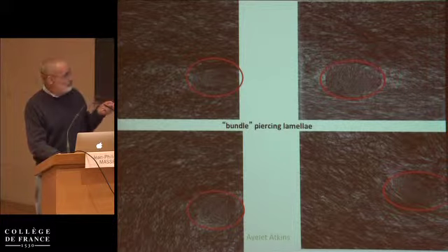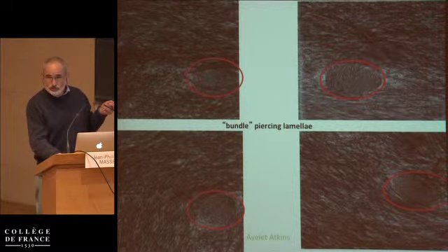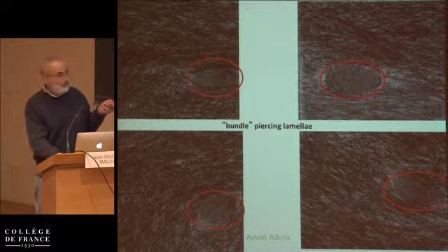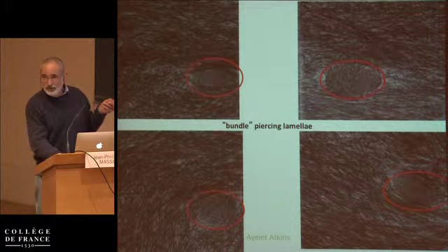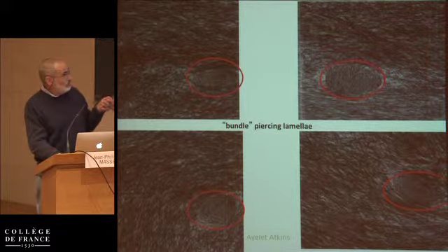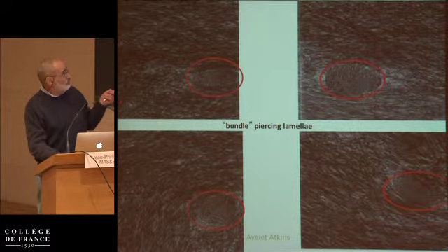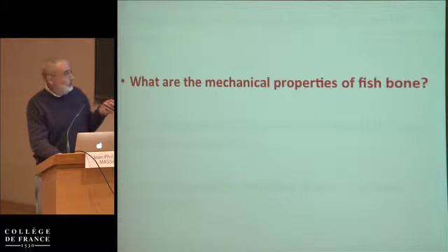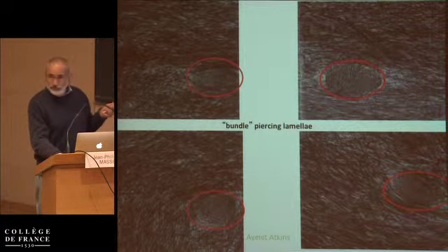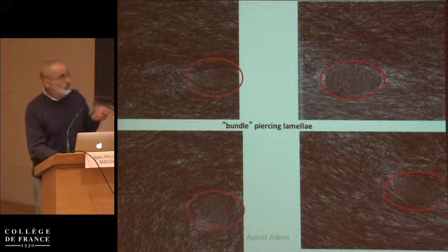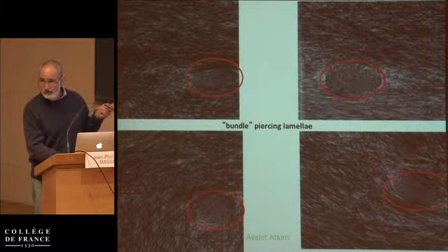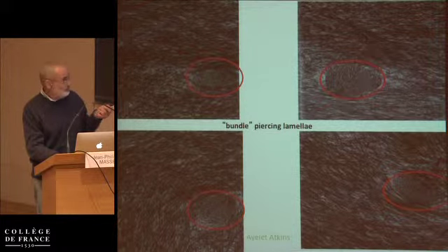these 1 to 2 micron diameter holes with what looks like unmineralized collagen fibrils, which are about 8 to 9 microns apart. And that's the reason we never, or almost never, see two of them. We have a few where we see the beginning of one and the end of another, because this whole thing is 10 microns. So this is our first clue that there's something unique about the structure, the lamellar structure, at least of the one fish species that we have looked at in this detail.